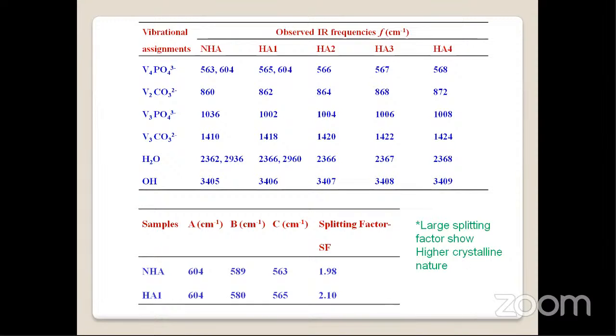See, the splitting factor is getting increased. For natural hydroxyapatite, it's 1.98. It is 2.10, but more or less it's the same. But there will be some slight increments. One can see the slight increment behavior. This kind of slight increment of splitting factor shows higher crystalline nature of the sample. So this study supports powder X-ray diffraction analysis.